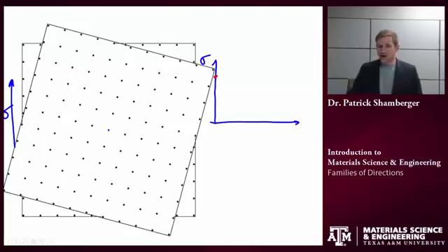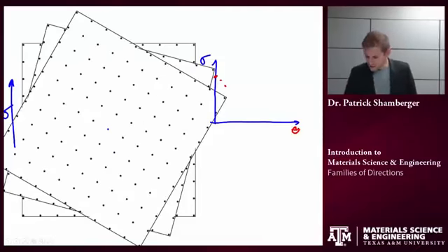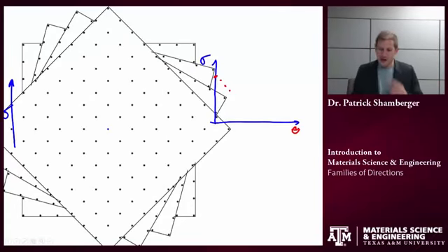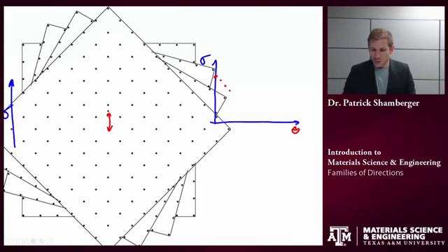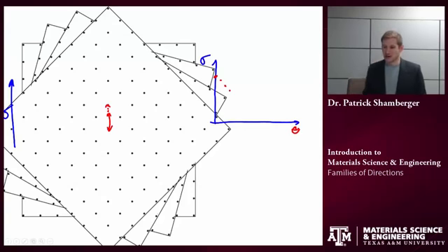So let's do the same thing, but let's rotate the lattice. Now I'm still measuring in the same original orientation, so all that has changed is the rotation angle of that lattice. In this case, maybe the electrical conductivity has decreased a little bit. I can measure that again and again and keep rotating it each time. I'm going to get a slightly different value for that property because the structure of this lattice is different in those cases. You'll see I went from originally having a very close spacing between neighboring lattice points to something where I had a much greater spacing between the lattice points. So maybe that's why I'm seeing a change in the physical properties.